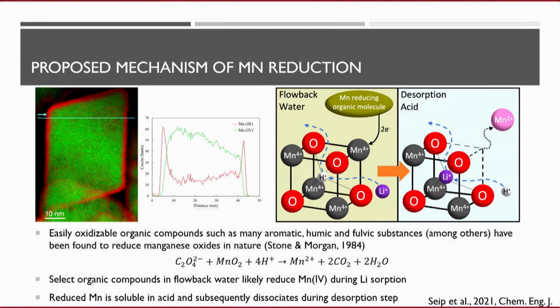What's happening, you can see on the outside very beautifully in this, we collected this at McMaster, is a red rim which is reduced manganese, either manganese 3 or manganese 2. And this is what happens to the mineral when it's exposed to the brine. We found that the reasons are two. You can see that further over in the schematic. There's organics in there that can reduce the manganese on the outside, and also hydrogen sulfide in the brine can do this. So when you get the reduction in the flowback water or in the brine, you put it in the acid to recover the lithium, and that reduced manganese enters into solution. This process is called reductive dissolution. So we're trying to inhibit this.